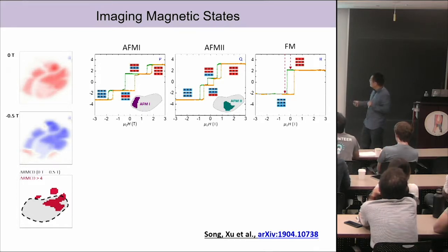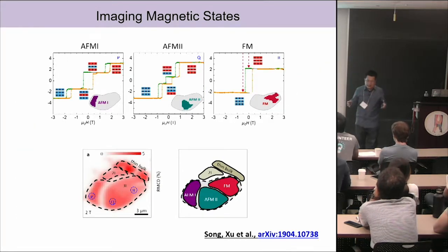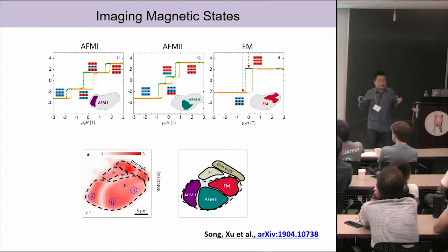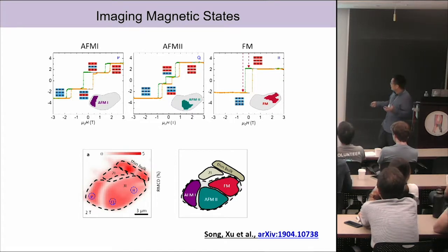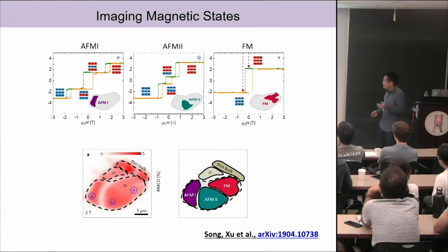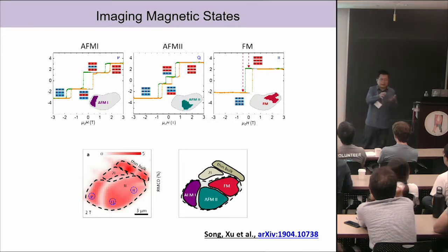Okay, so by doing this, we actually map out the area for these different magnetic phases. As I show you here, we have antiferromagnetic state 1, antiferromagnetic state 2, and ferromagnetic states. So this is just a simple example. We can control the pressure, control different layer stackings, and then control these magnetic configurations in the system.